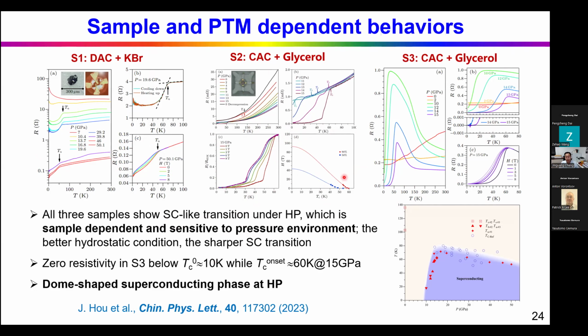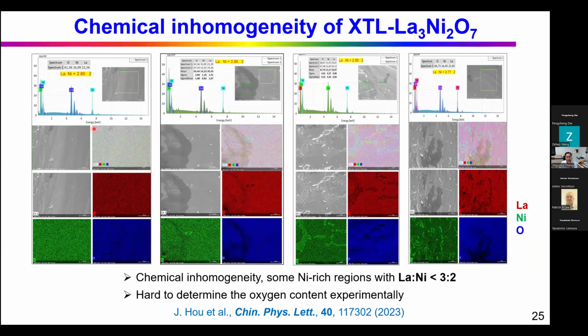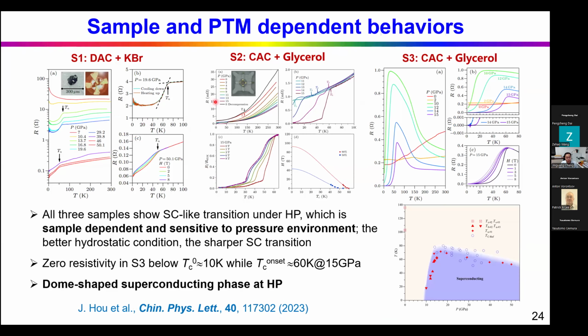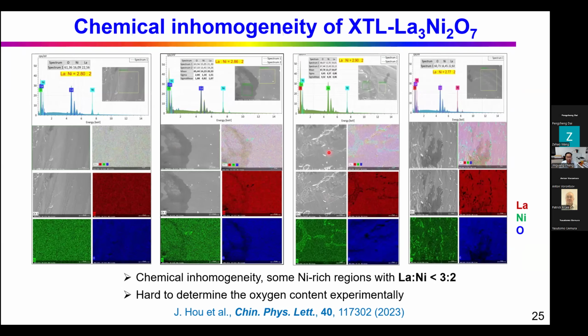So these are earlier studies on the single crystals. For these 3 samples, after we finished the high pressure resistivity measurement, we measured the SEM and energy dispersive spectroscopy. We found that there's some chemical inhomogeneity. This green color is for the nickel. In some regions, we found there are some nickel-rich regions, in a very small, micron size. So we confirmed that the crystal does not have very high quality, and there's some chemical inhomogeneity.